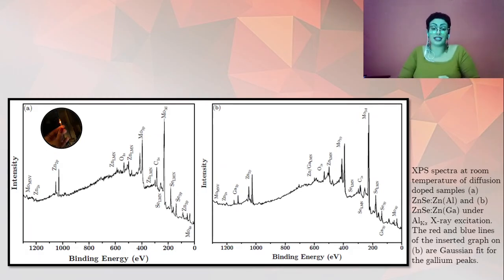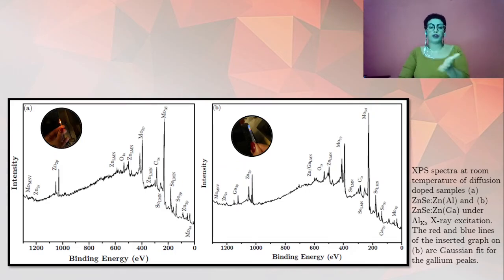On the other hand, the spectra acquired for the gallium-doped sample detected the presence of gallium after only one sputtering process. This indicates that the diffusion doping process was less effective in comparison with the aluminum-doped sample, concentrating gallium more on the surface than in the bulk. And this is consistent with the fact that the sample shows a not so strong luminescence.